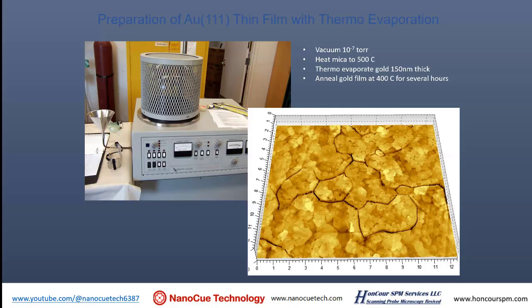You can see there are a lot of cracks there. That's very natural for the gold surface, because as you evaporate and grow the gold droplets on the surface, they grow tall. But between two droplets, because the orientation is different, they don't fuse together. They still maintain their separate grains. In a good sample, these grains are very big. In a bad sample, the grains are very small. Okay, so this is the surface of gold 111, and you can use that as a substrate to do a lot of your chemistry.